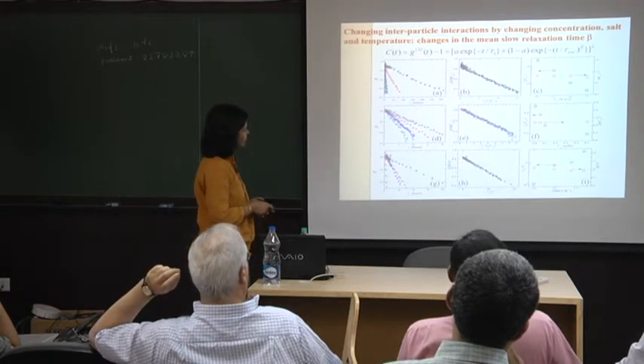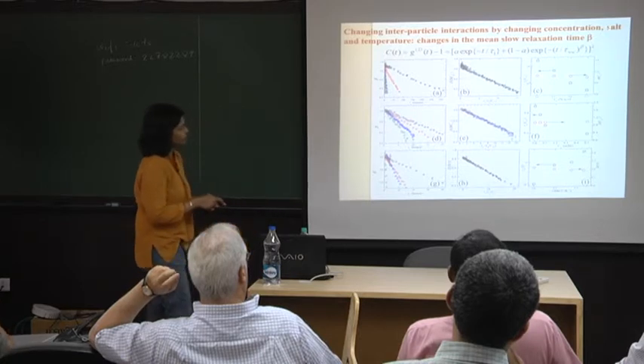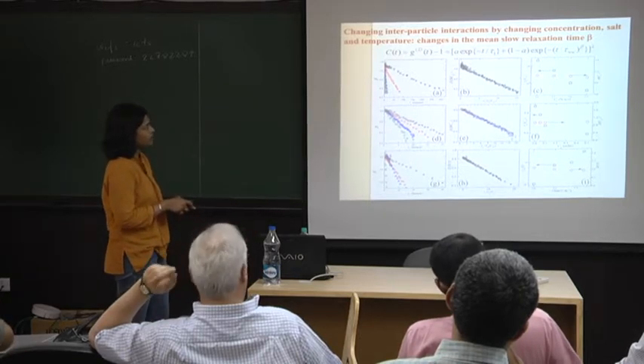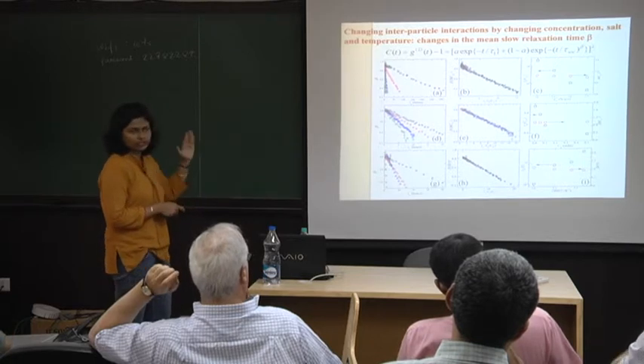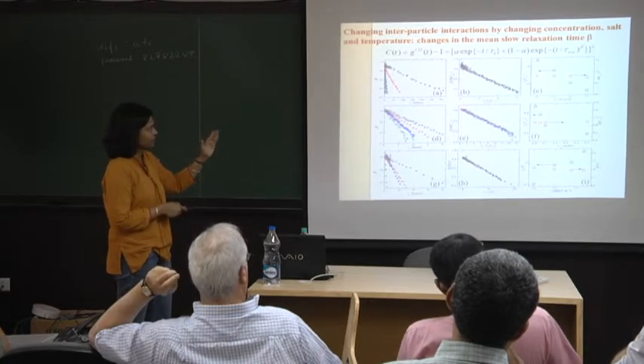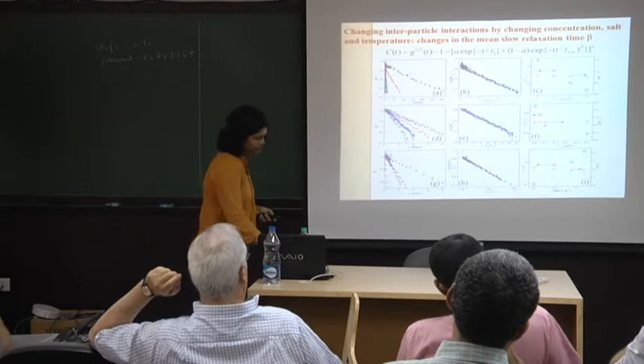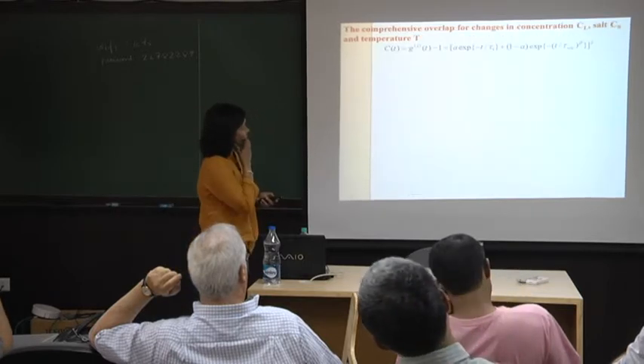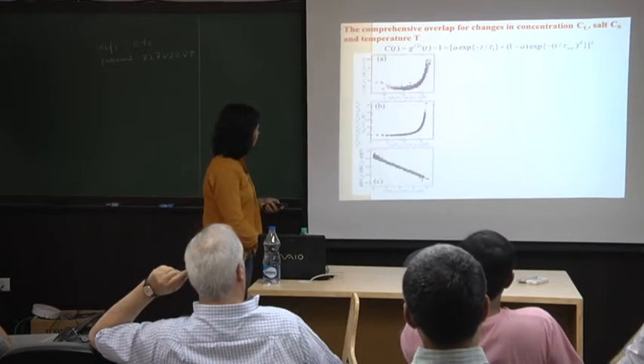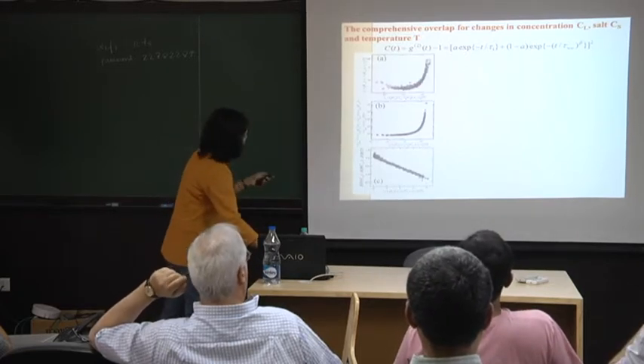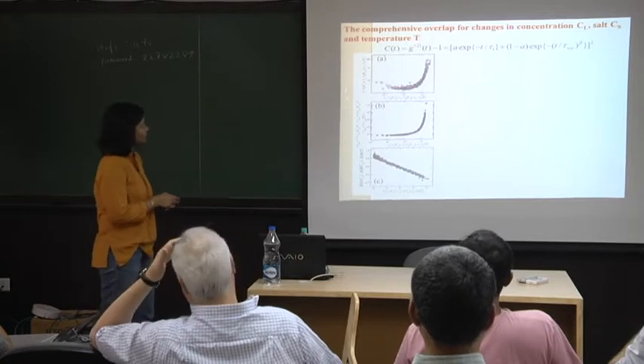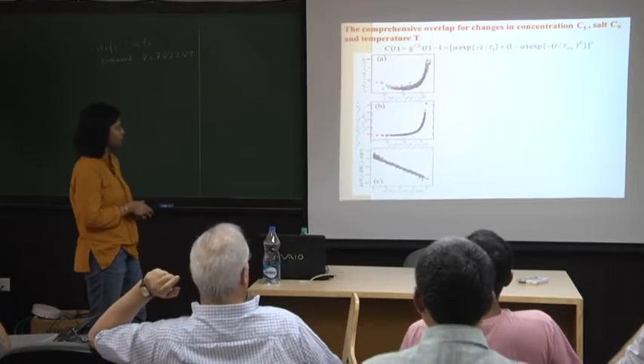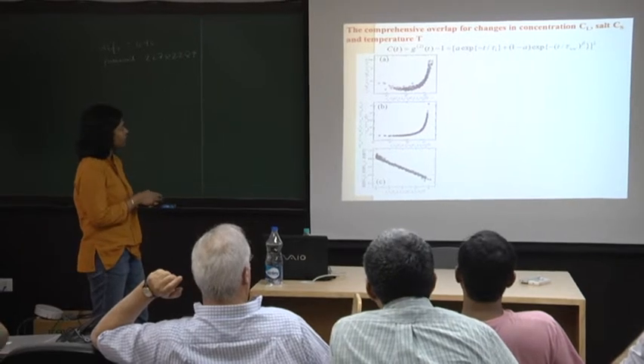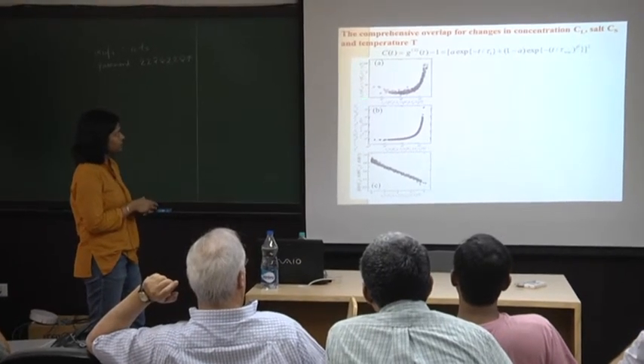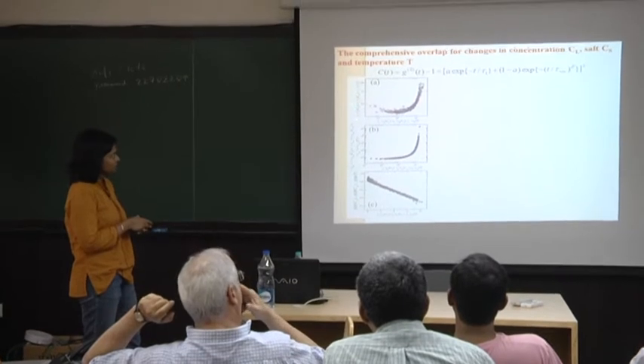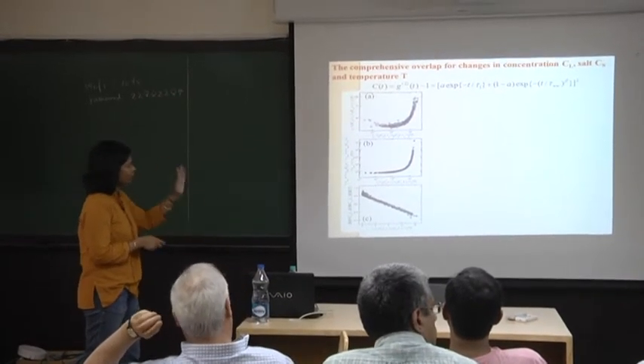I should mention here that when we scale the data for the stretching exponent as well as the beta relaxation time, we've used the same scaling for the x-axis. Okay? So now let's see exactly what's going on in the solution. So this is our master plot. Here we've taken the fast relaxation time, the slow relaxation time, and the stretching exponent. We have normalized the data by the shift coefficients for the different concentrations, salts and temperatures, and they overlap very nicely.